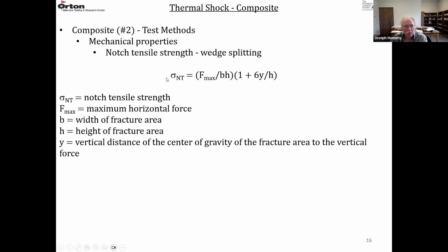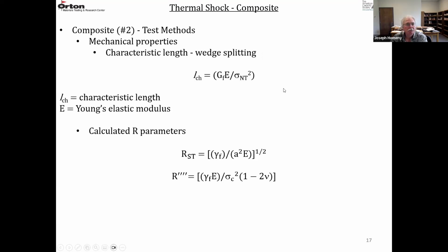So you can get a tensile strength. It's not a true tensile strength. It's called a notch tensile strength. It's not a pure tension. So you can get a strength from this test. You can also get what's called a characteristic length in the wedge splitting test. So LCH, for L characteristic, equals the fracture surface energy GF times the Young's elastic modulus, and that's divided by the strength, the notch tensile strength, squared.